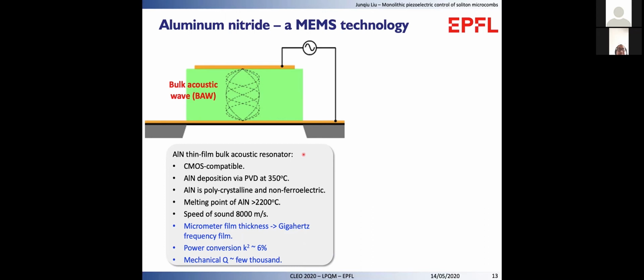The aluminum nitride thin film bulk acoustic resonator can be fabricated with a CMOS compatible fabrication process. The aluminum nitride can be deposited via physical vapor deposition at a low temperature, about 350 degrees. Aluminum nitride is polycrystalline and non-ferroelectric, and its melting temperature is higher than 2,200 degrees, which makes aluminum nitride suitable for extreme environments.